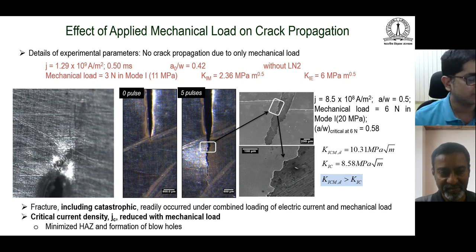Because of the electric current, if we have electroplasticity, that will affect the dislocation activity that can then affect the crystallization, recrystallization process. And then, of course, we also have this classical question of electromigration that can also lead to diffusion of the material. So what is the relative role of these? Let's say that if I call diffusion bonding, the temperature rise and the compressive stresses a direct effect of electric current that we can capture here in our FEM models.